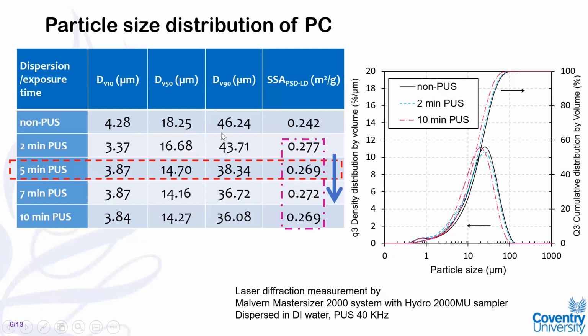As you can see in this graph, the result of particle size distribution, the change in specific surface area measured by laser diffraction shows a small change due to the ultrasound after 2 minutes. So this means that the ultrasonic treatment, even at 40 kilohertz, which is the highest ultrasonic energy used in this study, will not be really effective on deagglomeration of a finer size fraction, and has only a limited effect on the coarser size fraction of particles.